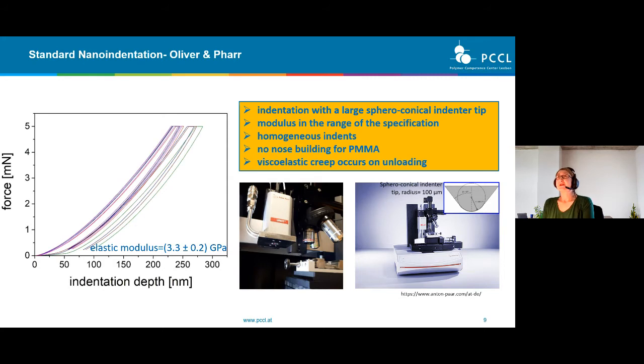So let's start with the standard nanoindentation, which is the previously described Oliver and Pharr method. Here on the left, you can see the indentation curves on PMMA. We did indentation here with a large spheroconical indenter tip. You can also see the tip form on the right side of the screen. The modulus we got out here with the Oliver and Pharr method is 3.3 gigapascal. So this is in the range of the specification of PMMA. Furthermore, the indents on PMMA are very homogeneous, and we cannot see any nose building like described before. But of course, the viscoelastic creep occurs also in the unloading phase.